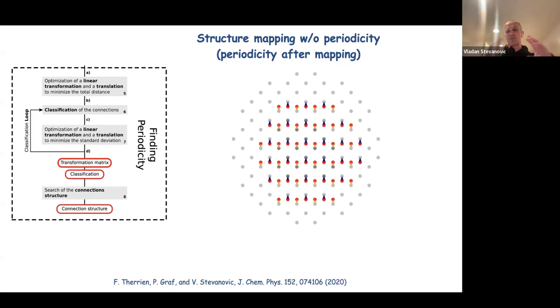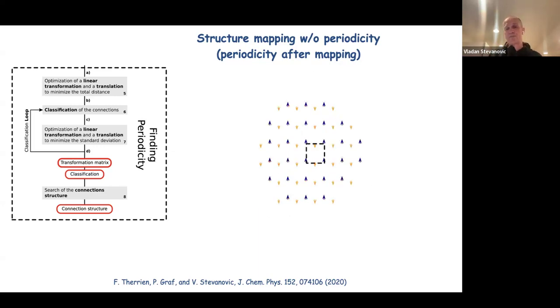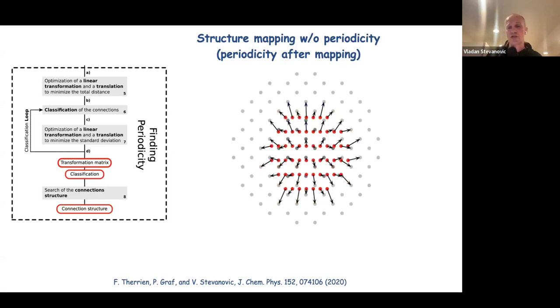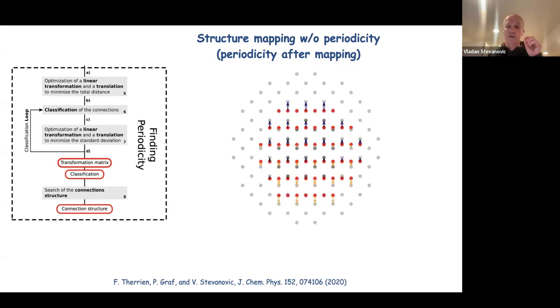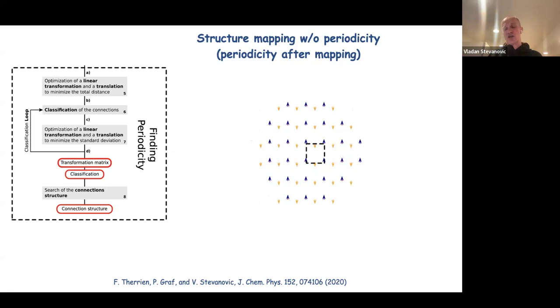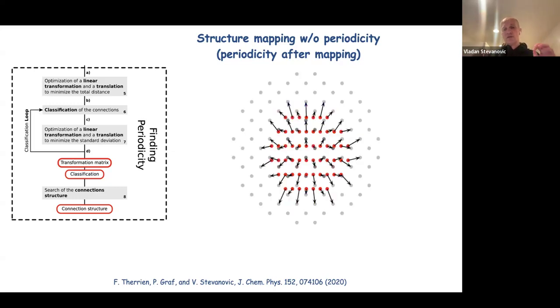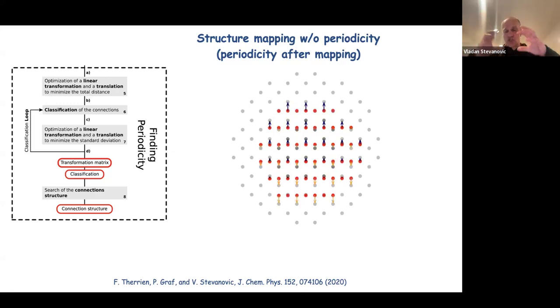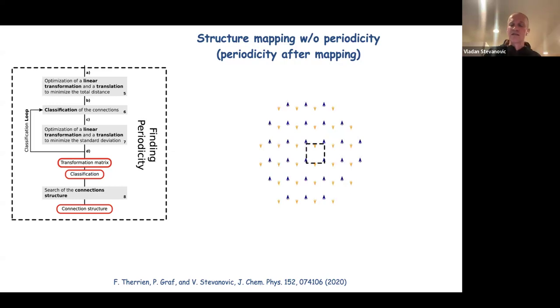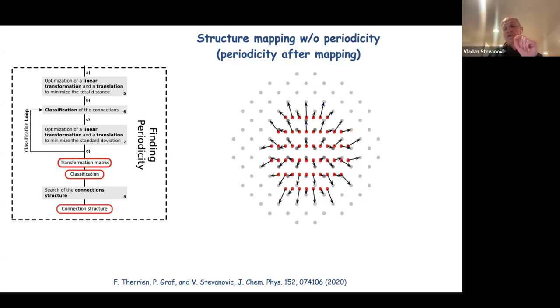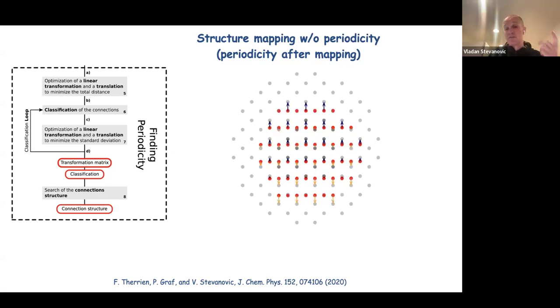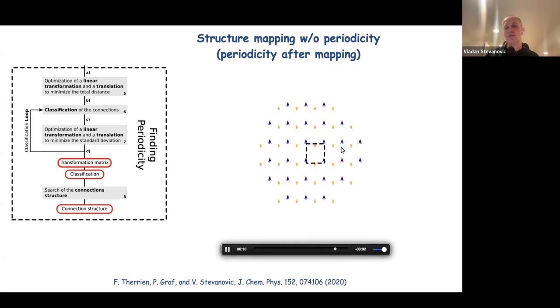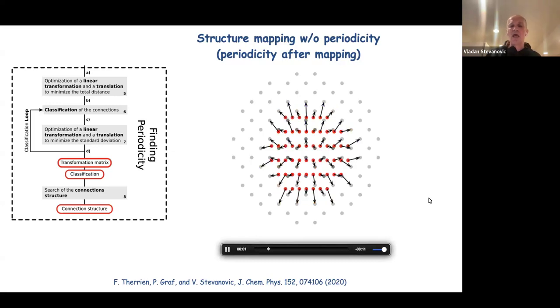And typically the arrows or the displacement vectors will then diverge if the volumes of the two structures are different, which is usually the case. Then if you include strain, so now you are allowing for the fixed mapping a strain of one structure relative to the other, then the arrows will shrink. Allowing strain will cancel the divergence. And then you can analyze the array of the displacement vectors and try to find some kind of periodic pattern in there, which in this little movie you can see as the box.